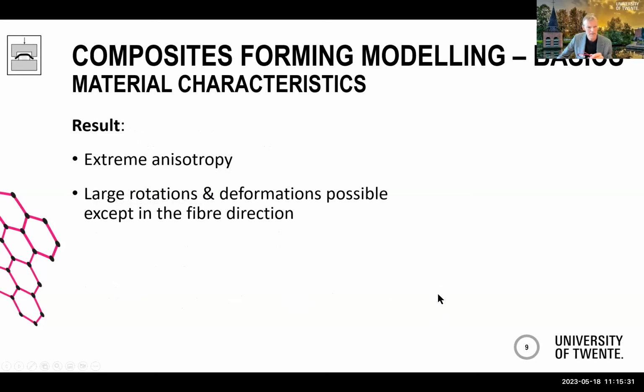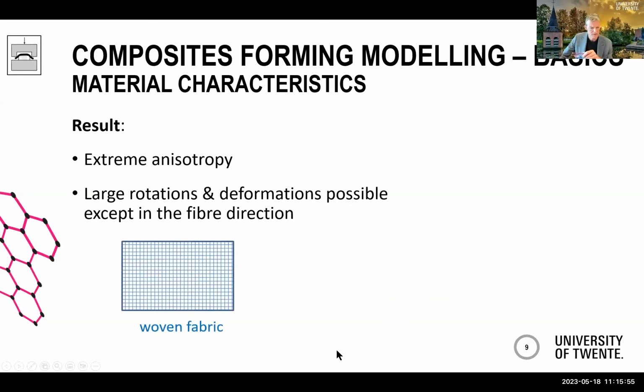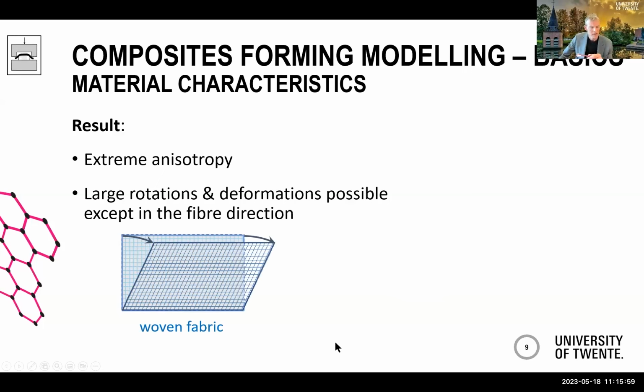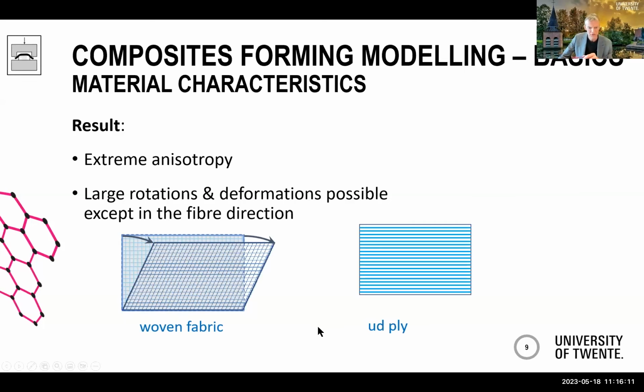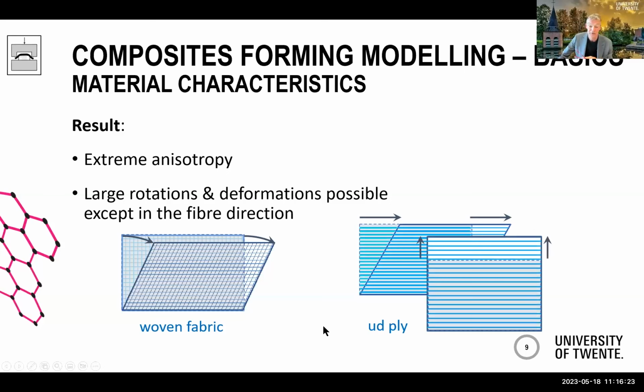And in this kind of material, large rotations and deformations are possible, except in the fiber direction. We would expect, well, let's say, negligible fiber extension during forming. If we would get significant deformations in the fiber direction, then I would guess something is going wrong. So let's say a woven fabric can get significant shear deformation, while the edges in the fiber direction remain of constant length. And for UD materials, obviously that can also shear more or less significantly, and it can also extend a bit in transverse direction, although to a very limited scale in practice.